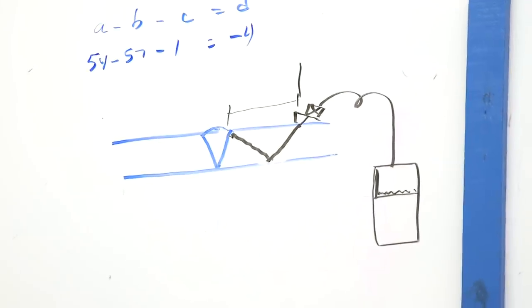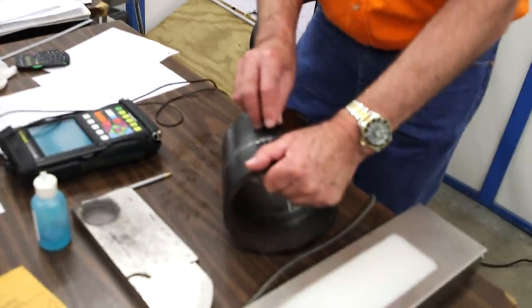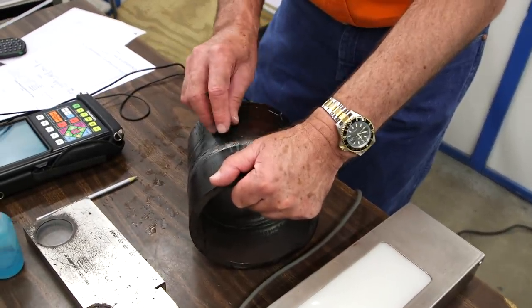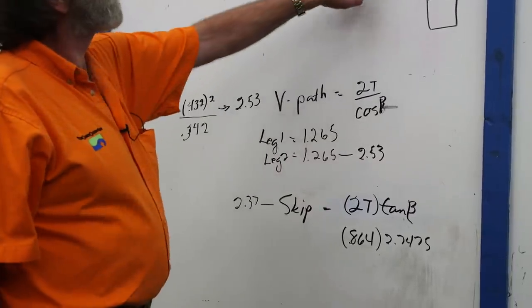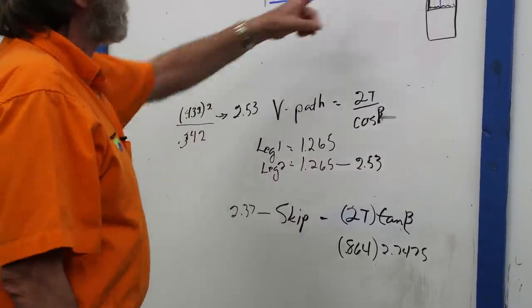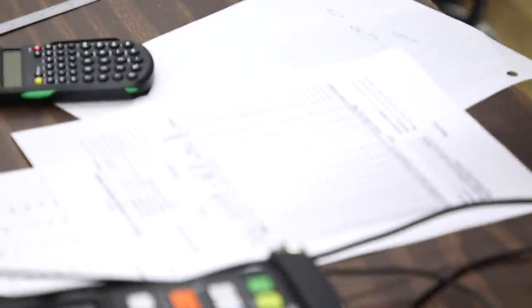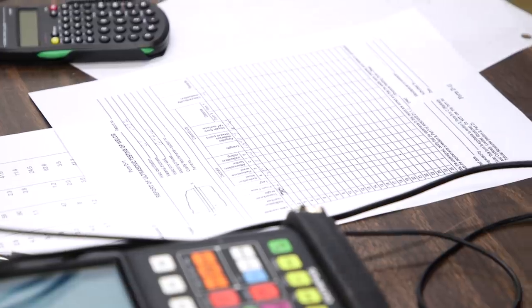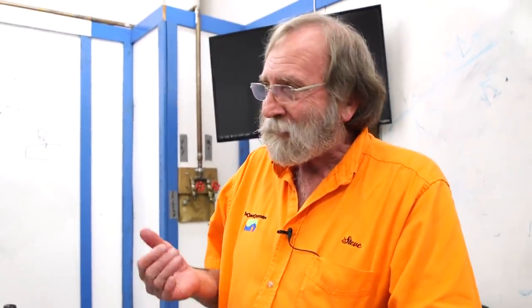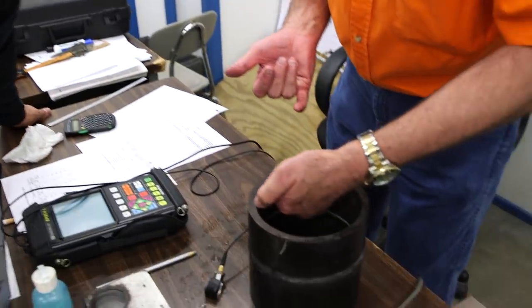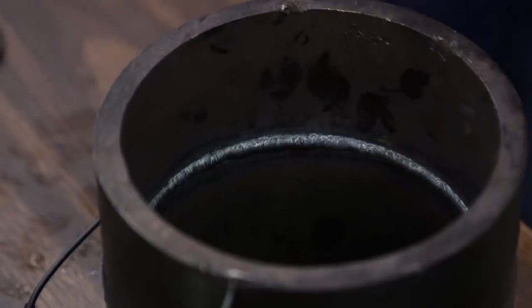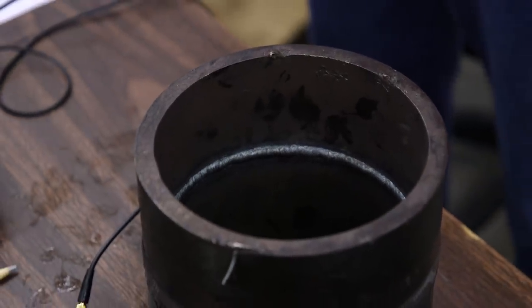So what did we have back here? Well, I started to look at this, and I started to get this all in the same spot. So I did some calculations over here, and I found out that area is roughly an inch long, look like it's 446 thousandths deep. Well, since this is only 432 thousandths worth, yeah, that sounds like we got more metal there than we do someplace else. Well, how do we get more metal? So let's look on the inside end. And we look at it visually, and sure as heck, there's a little spot here where the root is a little bigger than the rest of it. And that's what we're looking at here. So like I say, doing this will take you a whole lot of information, but you kind of got to know what you're looking for. Not just because it goes up or just because it reads higher. It doesn't mean anything.